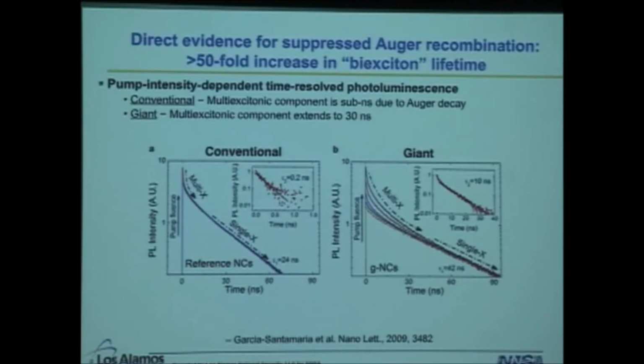And you can actually use this data to calculate biexciton lifetimes. So how long can a biexciton live? And that's just 2 excitons in a quantum dot. And it's only 0.2 nanoseconds in the case of conventional quantum dots. You do the same thing for giant dots, and you find that this multi-excitonic region actually is highly extended in time. And so now we calculate biexciton lifetimes that are 10 nanoseconds long.